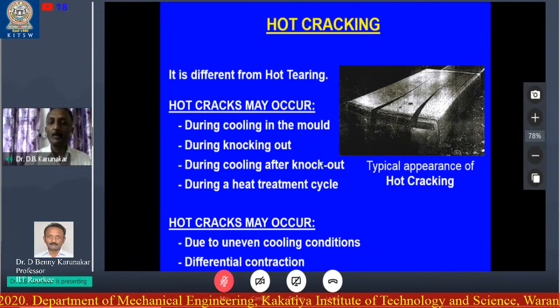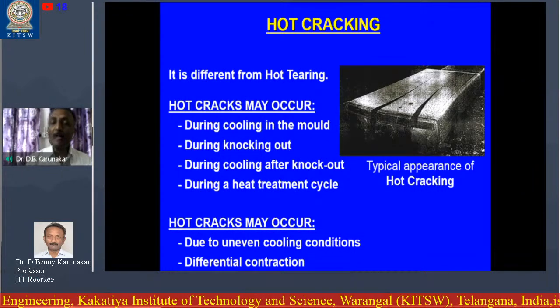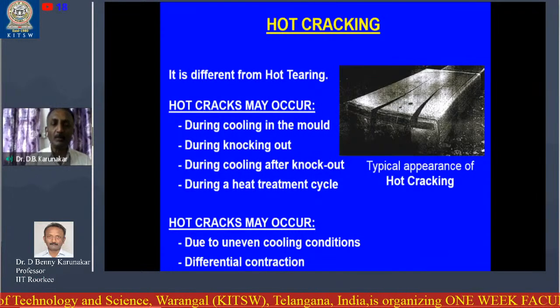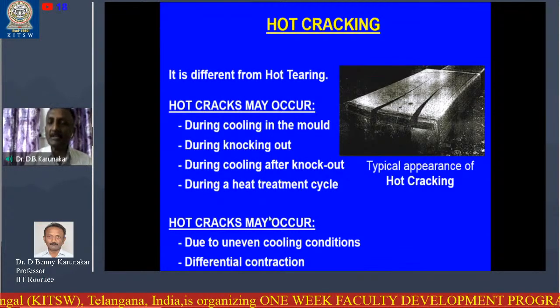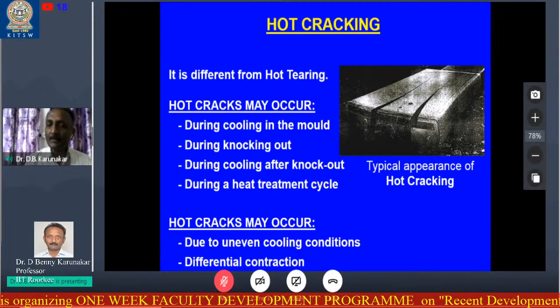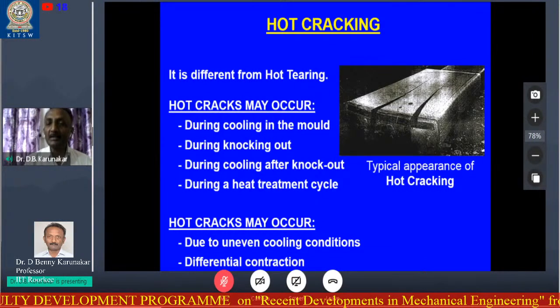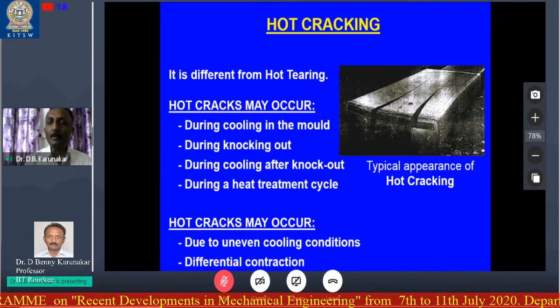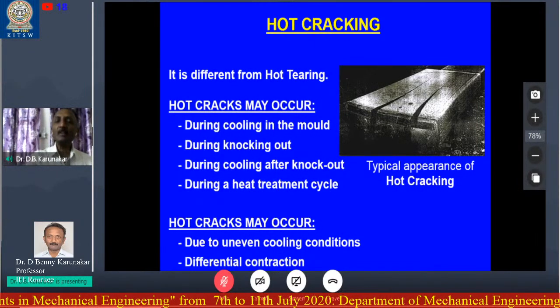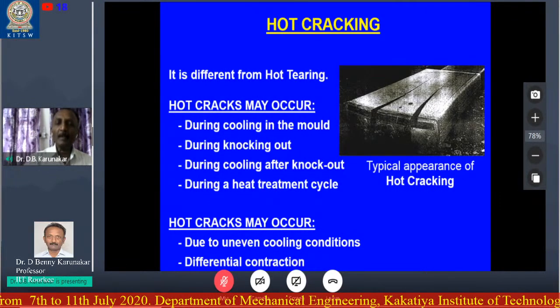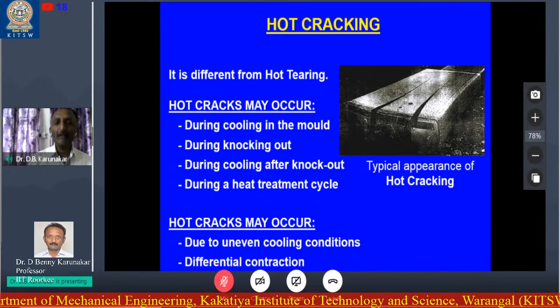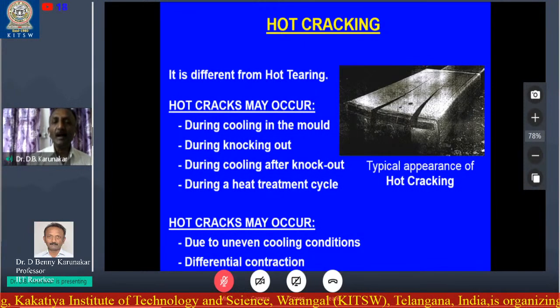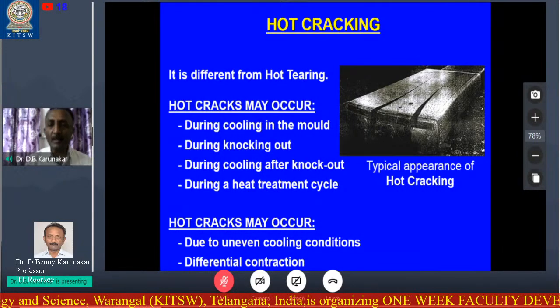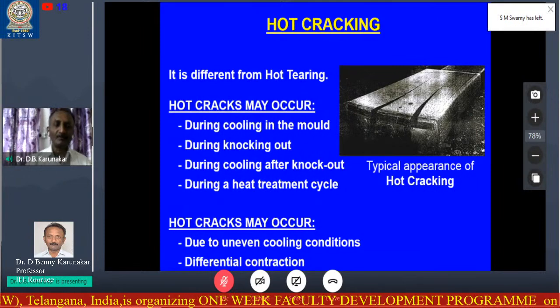During cooling after knockout, if there is uneven cooling, that can result in cracking. Or during heat treatment, after the casting is taken out, it can so happen that some sections have larger surface area, absorb more heat, and undergo more expansion, while a neighboring section with lesser surface area absorbs less heat and undergoes less expansion. That difference in expansion is how this cracking occurs, due to uneven cooling conditions and differential contractions.